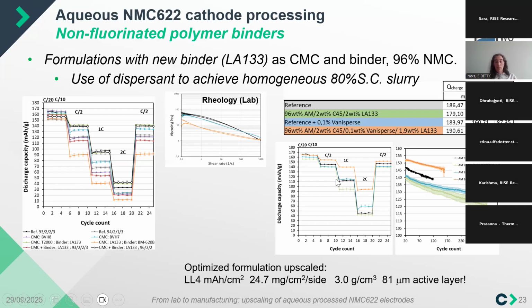Still, in some cases, needing this pH regulator to keep the pH at around 9, not much higher than 9, which is the other key point. And also adding some additional dispersants or alternatives to CMC, since CMC is brittle and creates cracking and delamination issues that I showed in some of the initial slides. So, for instance, in this case, we have tried Vanisperse, which is another type of dispersant and not a cellulosic paste.